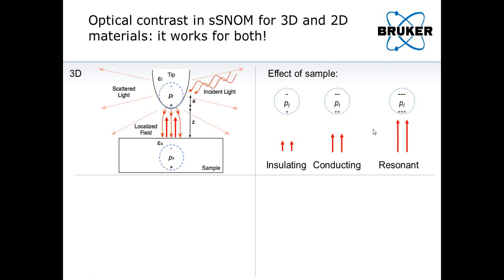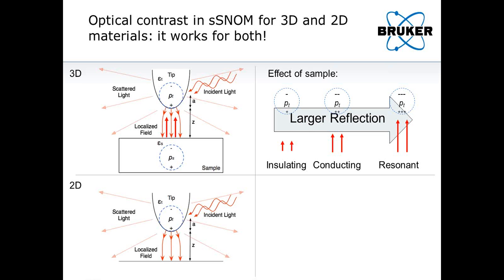There's a subtlety here: a resonant material can actually cause destructive interference. It can reflect light such that the phase is different than the phase of the driving light that drives the dipole in the tip. So a very resonant material can actually have a smaller tip dipole. Basically, as you go from left to right, you have larger reflection, and that's how you get information about the sample.